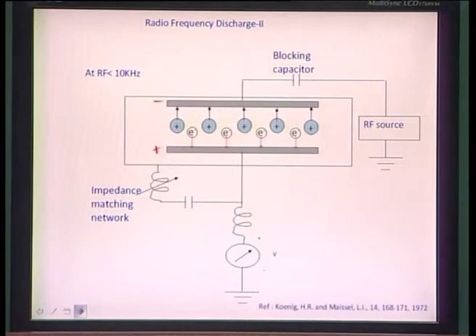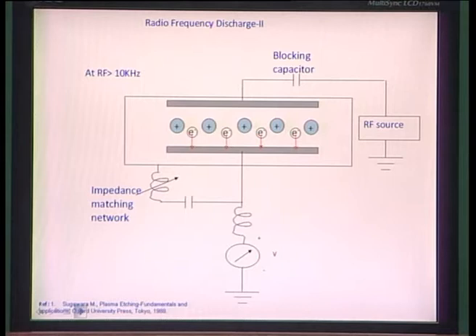And one more important factor is that beyond a certain frequency, which is typically about 10 kilohertz or so, the behavior of the ions changes slightly. Below 10 kilohertz it is almost always that the ions and electrons move in parallel and go towards the opposite plate, and as you change the polarity they also change the direction of their motion. But above 10 kilohertz the field is too fast for the heavy ions to follow the field, as a result of which it is only the electrons which go around and the ions remain static within the bulk of the plasma,